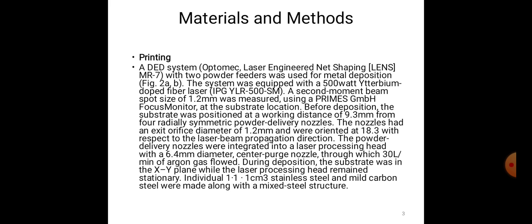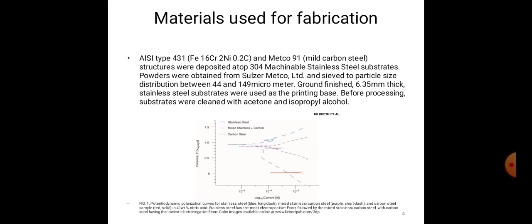Now materials and methods. Basically in the printing method, the DED system, that means Optomec Laser Engineered Net Shaping, MR7, with two powder feeders was used for metal deposition. It is shown in the figure on the next slide. The system was equipped with a 500 watt ytterbium-doped fiber laser, a beam spot size of 1.2 mm, and a flow setup that is shown in my slide. Materials used for fabrication: AISI type 431, Fe16Cr 2Ni 0.2C, and Metco 91, meaning mild carbon steel, as followed by this slide. Structures were deposited atop a 304 machinable stainless steel substrate. Powder was obtained from Sulzer Metco.